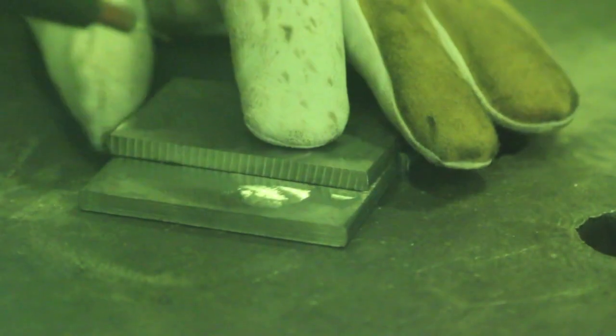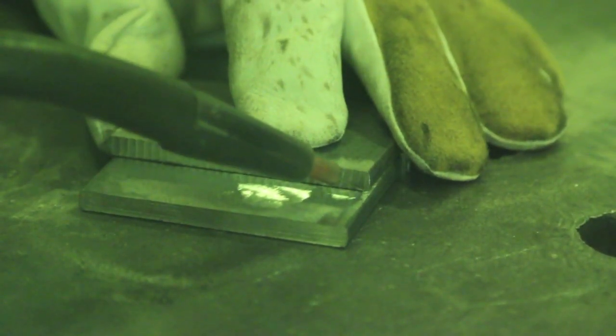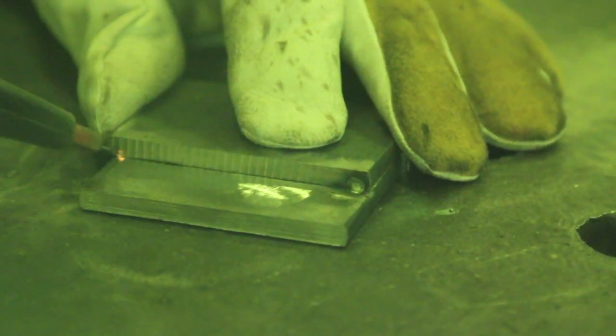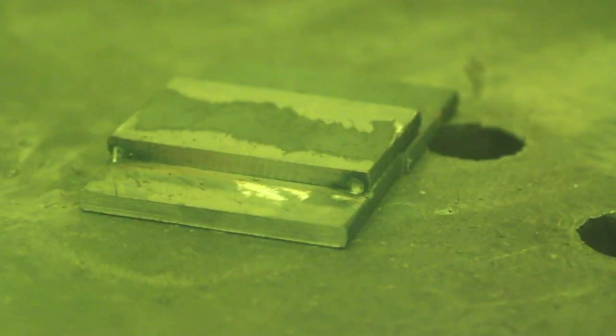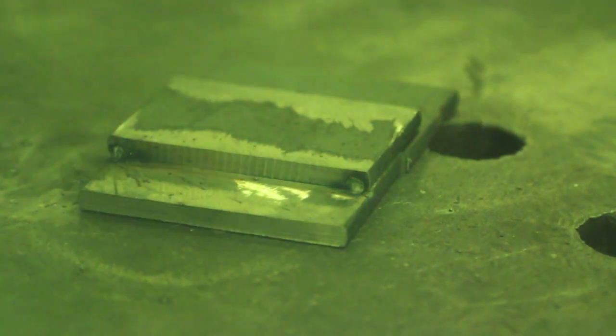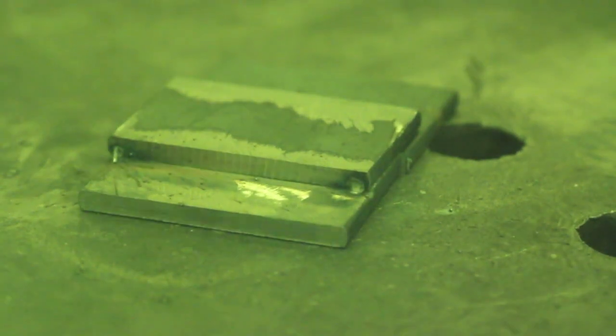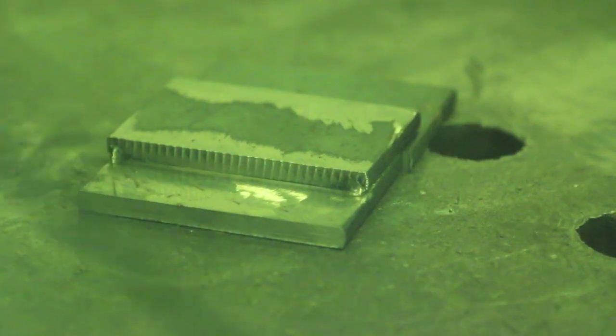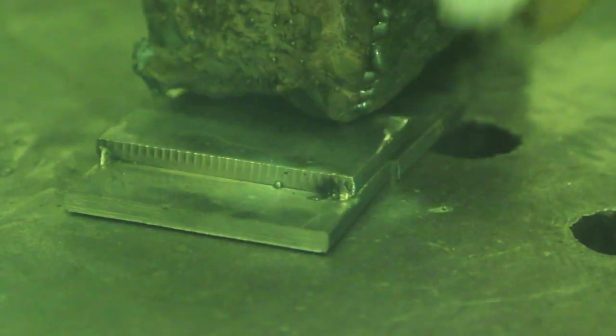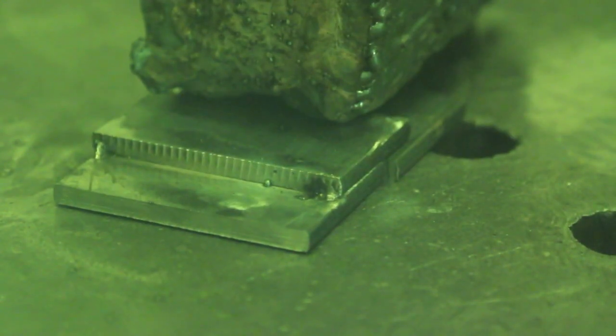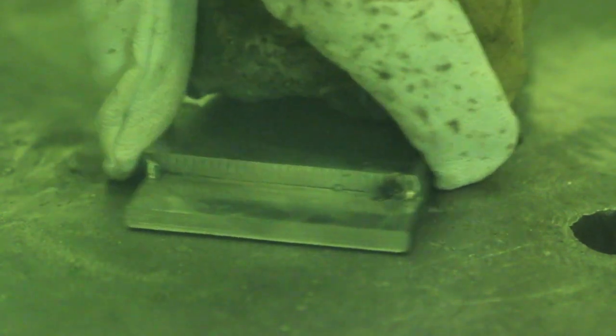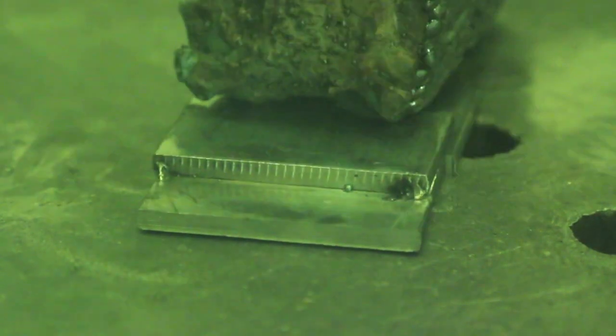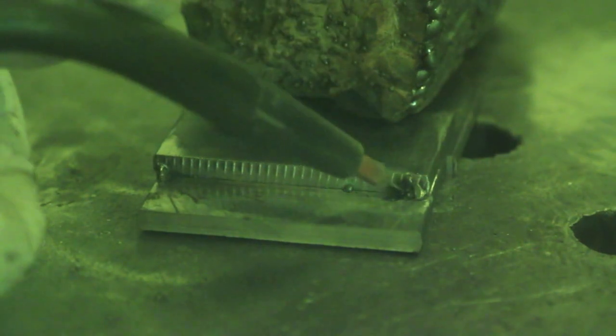We're going to begin with tacking this up as I just mentioned. Very simple procedure. Just get it right in the corner there and give it a little shot. Enough to where it basically fuses a little bit, enough to hold it in place. But not too much. We don't have to get excessive with a tack weld. Notice I purposely left this part of it in here. I'm cleaning off the tack welds with the grinding wheel. Of course you could use a chipping hammer or a regular hand brush or whatever. But I wanted to point out that when you have something that produces slag, you must clean your tacks or previous welds before you actually start welding over it. You do not want to trap slag in between there. Very important point.